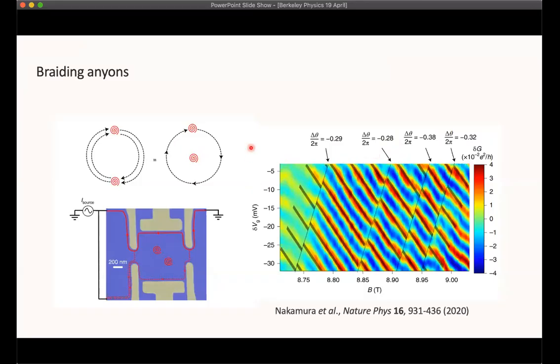Now, if you've done your fractional quantum Hall effect homework, then you're familiar with this indicating that, in fact, the particles that are contributing to conduction are actually quasiparticles, and they're anyons. They're anyons that obey neither fermionic nor bosonic statistics, and the prediction of 1/3 of 2 pi for a phase slip is exactly what you would expect in this case of the 1/3 fractional quantum Hall effect.